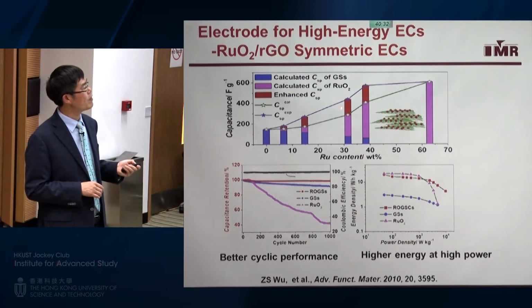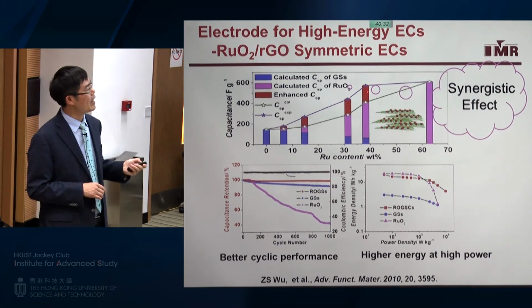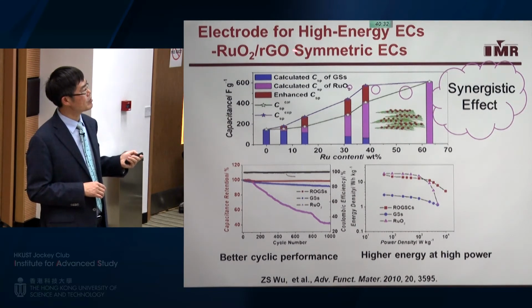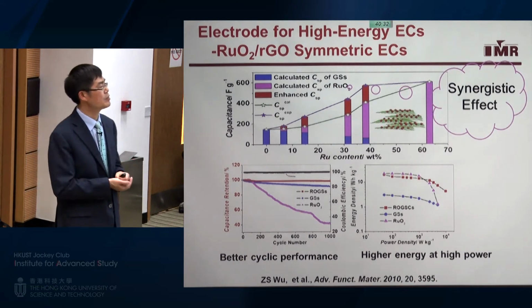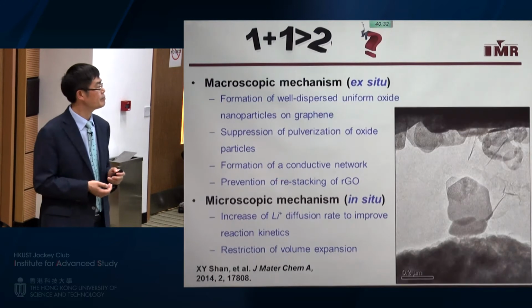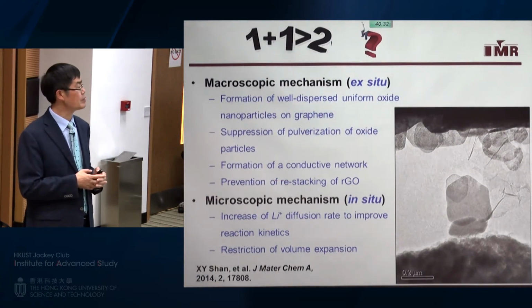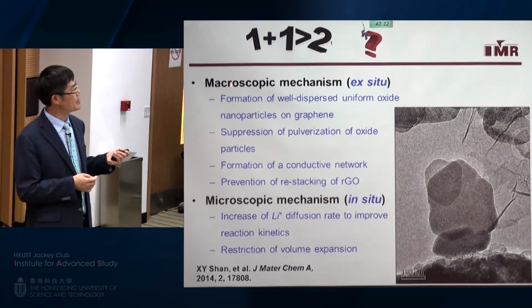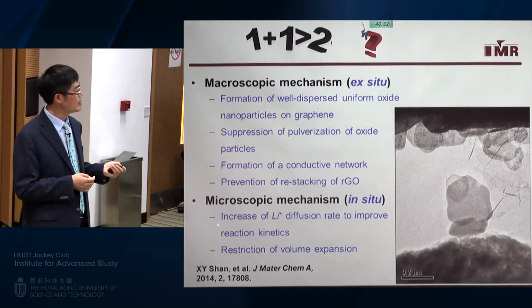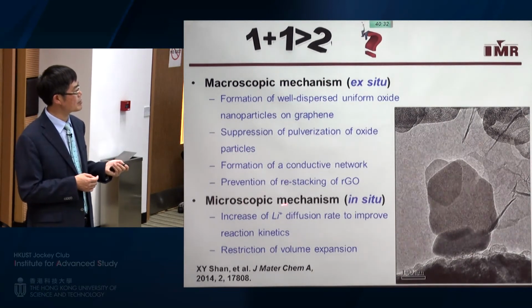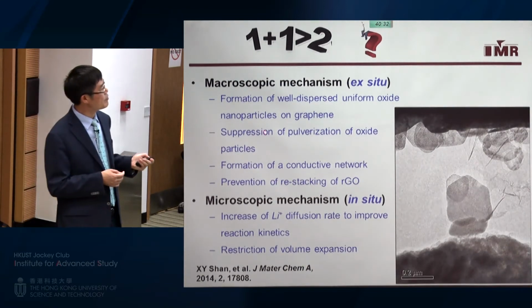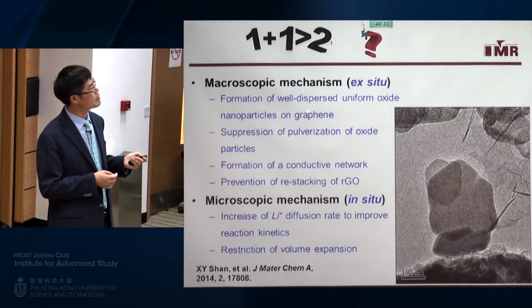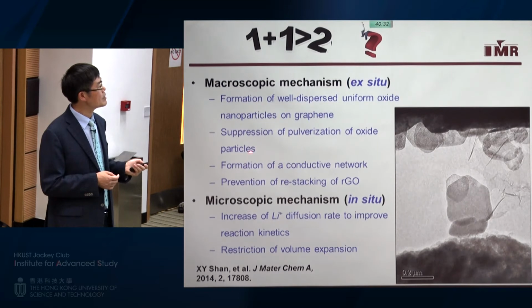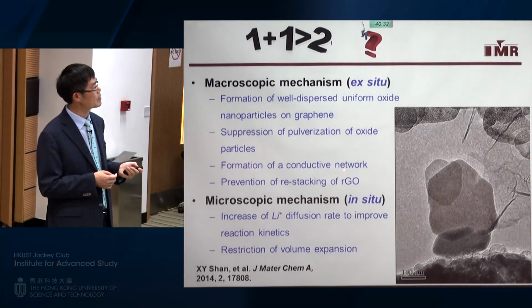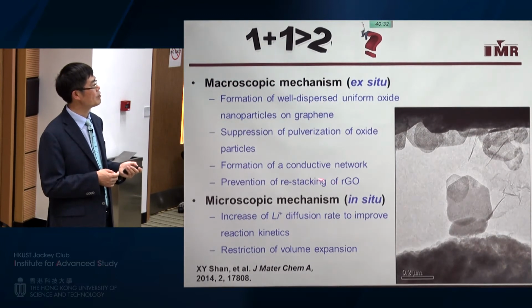And based on the rule of mixture, we found that we have a plus capacitance here, which means between the oxide and the reduced graphene oxide, we have some synergistic effect to improve the performance. So what is the mechanism for those materials? We have investigated it in a macroscopic way and also a microscopic way. As I mentioned before, with graphene, we can form well-dispersed oxide nanoparticles, and also we can suppress the pulverization of oxide particles, form a conducting network, and prevent the restacking of reduced graphene.